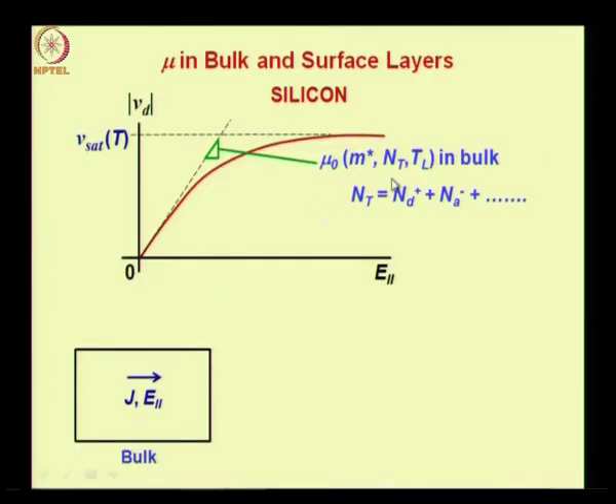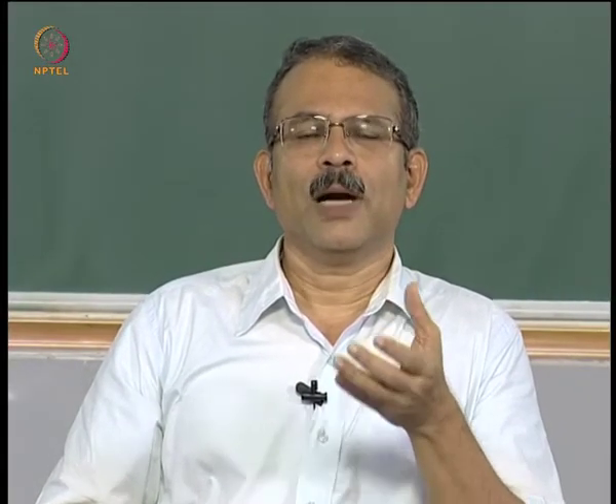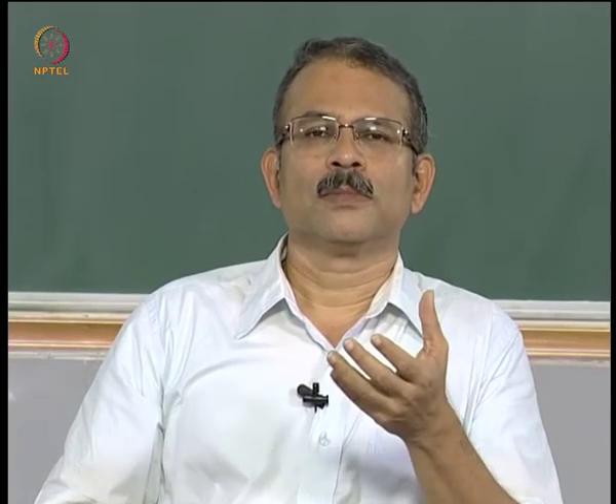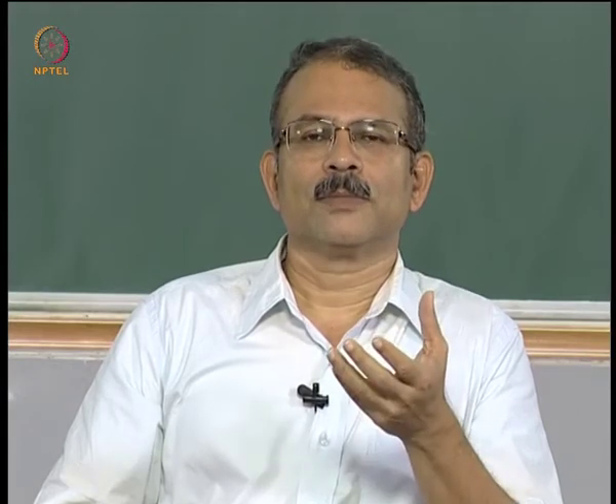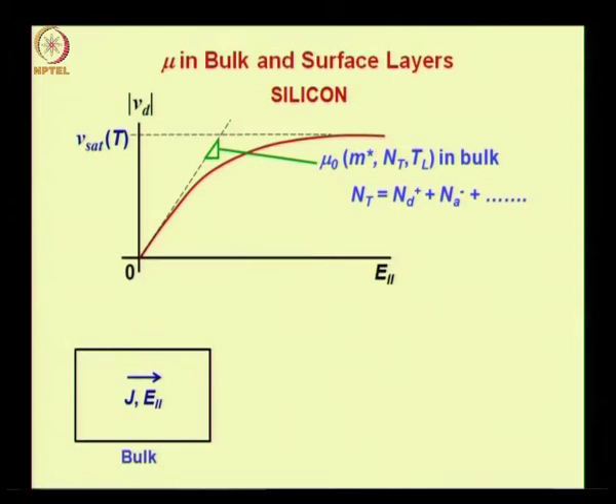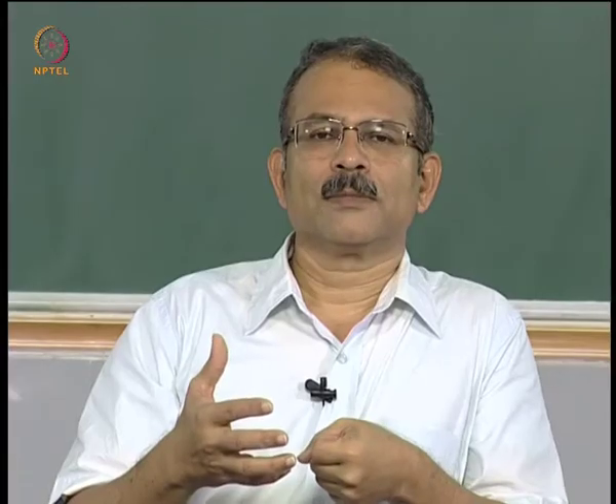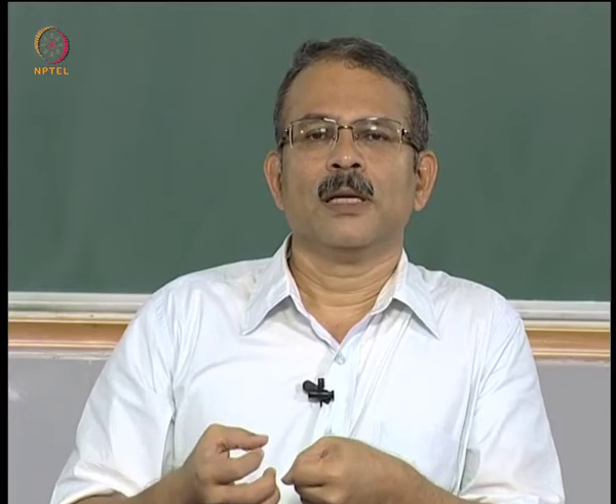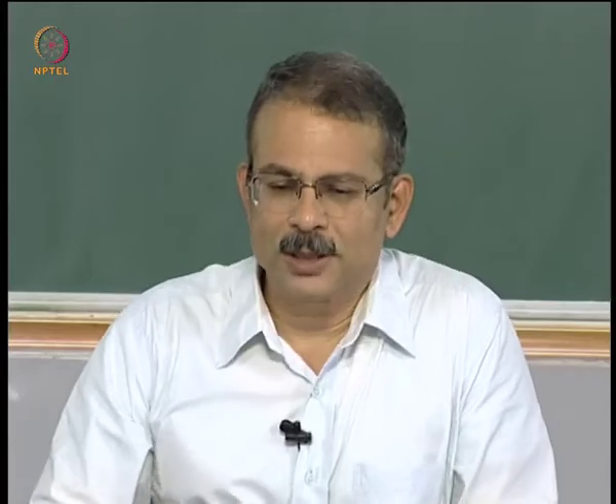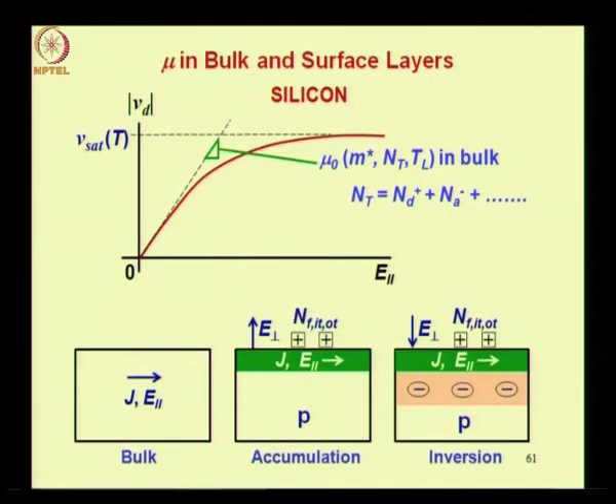In addition to the impurity concentration, you have the dependence of mobility on lattice temperature as well. So you would recall that we had said that the electron or hole gets scattered by ionized impurities, by phonons and by other carriers, right. So therefore the behavior of mobility is a function of N_T and T_L. It depends on effective mass, because between two collisions the amount of velocity that the electron acquires because of the electric field depends on the effective mass. Lesser the effective mass, more the acceleration and more the velocity. Now let us look at the surface mobility picture for the surface.